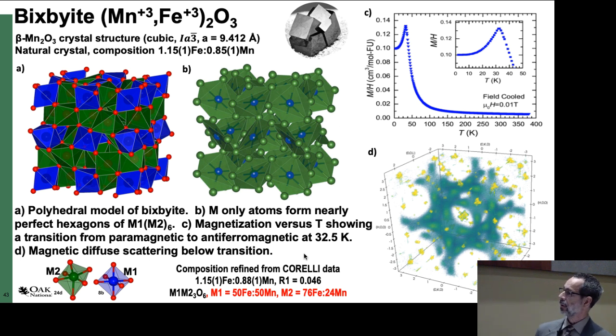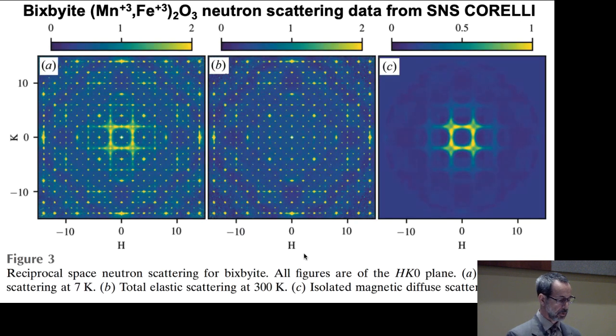This is the reciprocal space map of the diffuse scattering that we recover from the CORELLI instrument. So if you look at the fact that the magnetic scattering turns on at low temperatures, below 32 Kelvin, we can isolate the magnetic-only diffuse scattering simply by subtracting the room temperature from the low temperature, and we end up with the magnetic-only diffuse scattering.